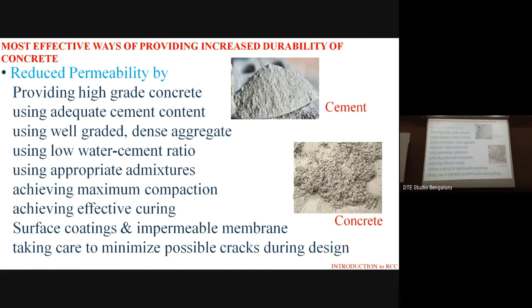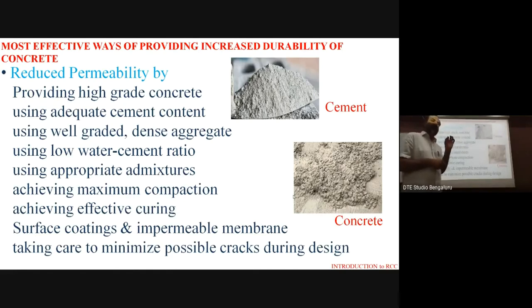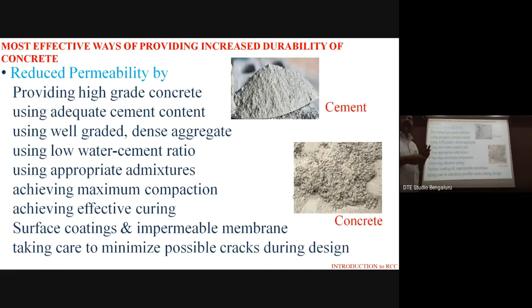Another most important factor in achieving durable concrete is the water-cement ratio. We must make concrete such that each and every particle of cement reacts with water. A low water-cement ratio gives the most durable concrete. The water-cement ratio, which depends on moisture content in aggregates and atmosphere, should typically be around 0.4 to 0.5.